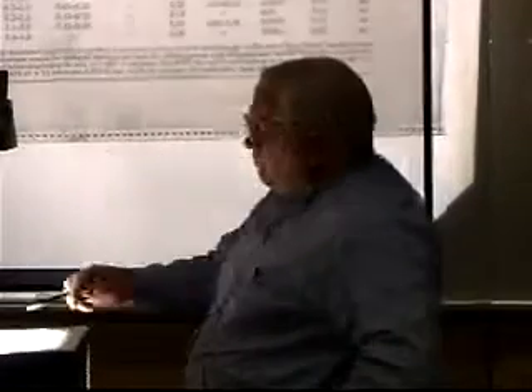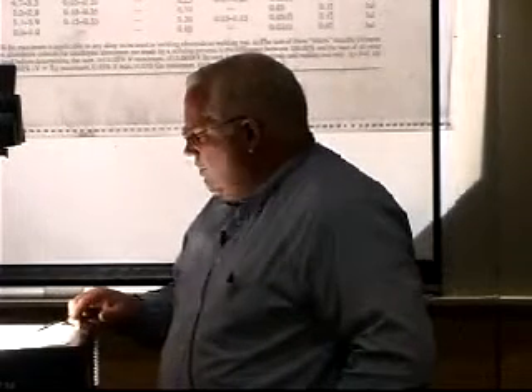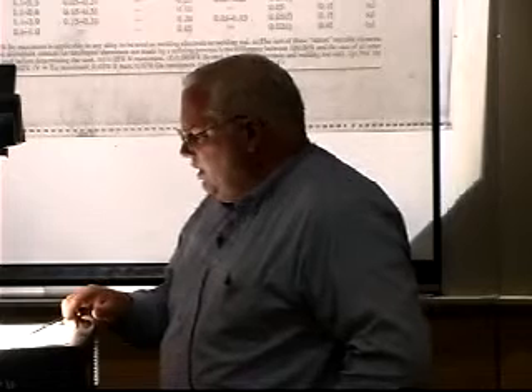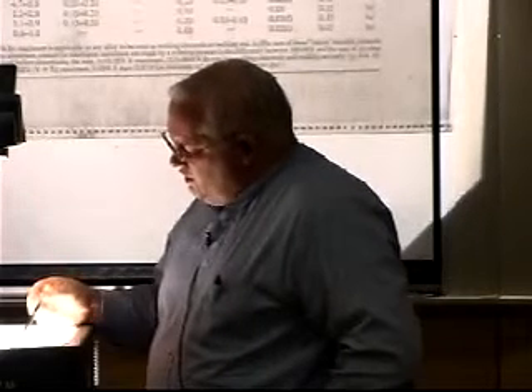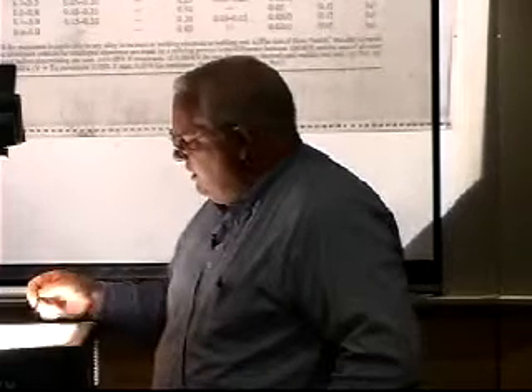Now, you don't have to try to read this, but these are a bunch of different aluminum alloys going down here, and all I really wanted to show is this is iron. There's not a lot of iron in these things. There's not a tremendous amount of copper in most of these alloys. There is 3.3 to 4.7. There's a lot of copper in that alloy, but everything else is down less than 0.3% copper.